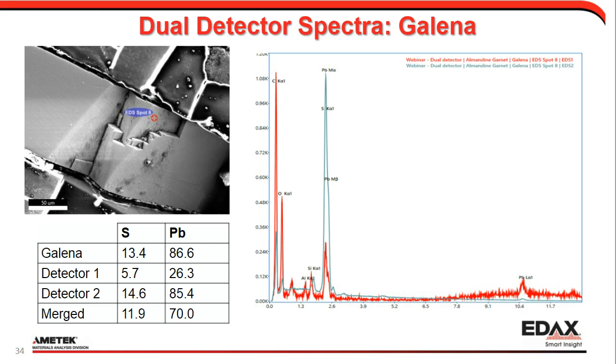And if I look at the low energy range, we can see our main sulfur lead peaks are heavily attenuated and we get a lot of carbon and oxygen. So what is happening here is that we hit the sample and we generate X-rays right where we're hitting.